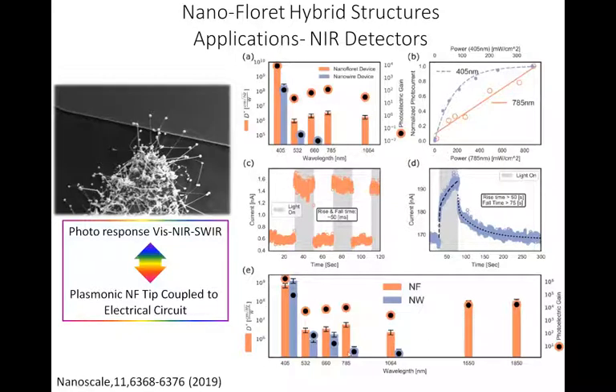So you can see that as a function of wavelength, while detectivity and photoelectric gain of nanowires diminish at longer wavelength here, you can see that for the nanoflorets, it is stable and even increases at the near IR. And this was an opening for a whole bunch of architectures that can utilize this bridging effect with the nanowires that are coupled with a plasmonic antenna at the tip.